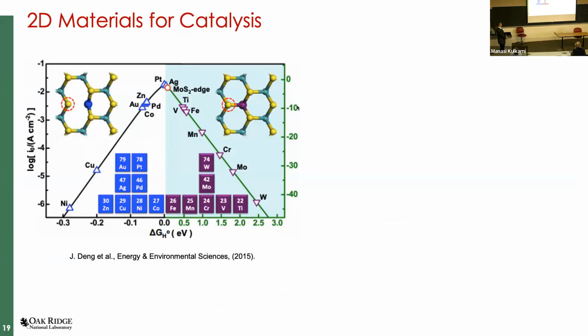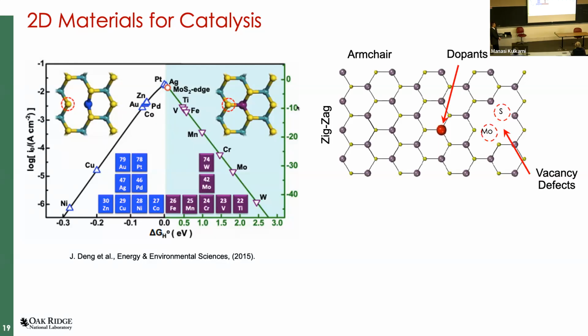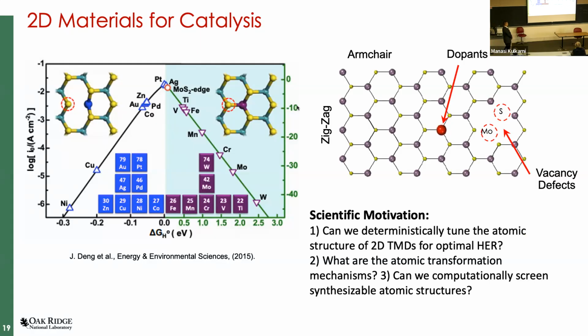But you can take some of these 2D materials, and originally they're not catalytically active. So if you take a 2D material and pop it in a fuel cell to do an HER reaction, it's not going to be active. And that's because the basal plane is just extremely inactive for catalysis. However, if you start to dope it, if you start to modify it by creating defects, if you change the armchair configuration, it changes the zigzag configuration at the edge, perhaps you can increase the catalytic activity.